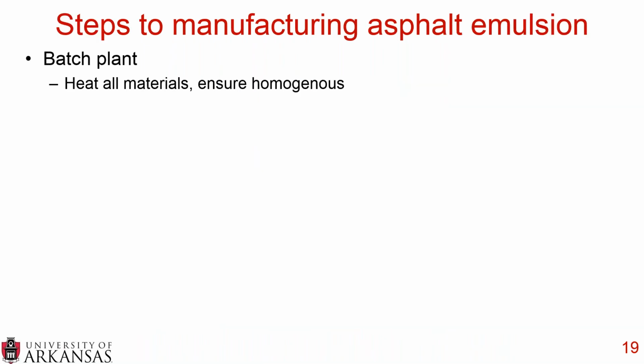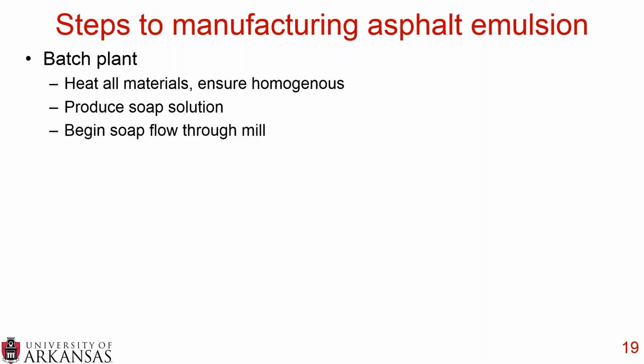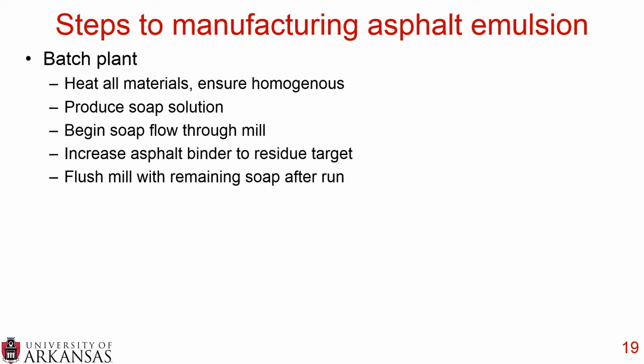Now I'm just briefly going to go over the steps to manufacturing asphalt emulsion. If you're in a batch plant, what you're going to do is you're going to heat all those raw materials and ensure that they're homogeneous. You want to produce your soap solution, and you want to begin your soap flow through the mill. Then you increase the asphalt binder into the mill until you hit your residue target. So if you're aiming for 66% asphalt binder residue in your asphalt emulsion, you just slowly dial it up until you hit that 66%, and then you're good to go. When you're done making your run, you flush the mill with the remaining soap to clean it out, and then you can make your next product in a batch plant.